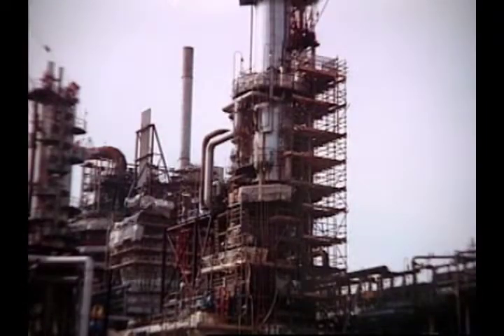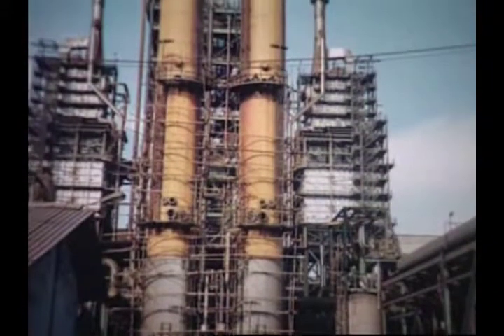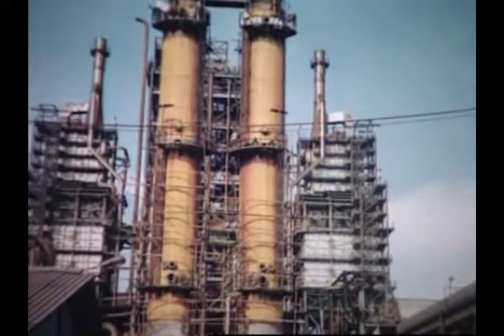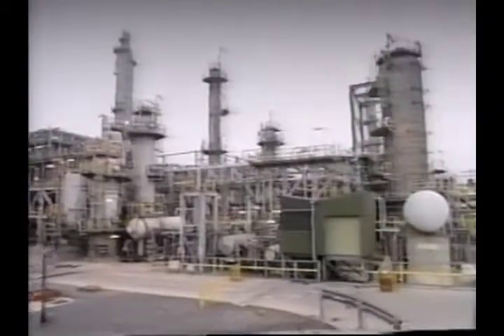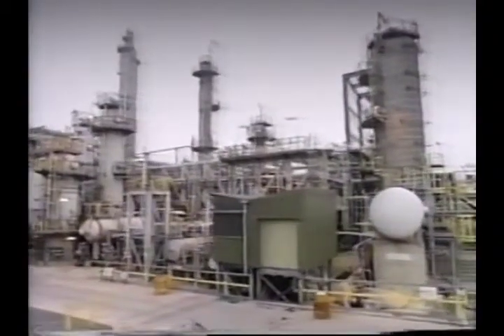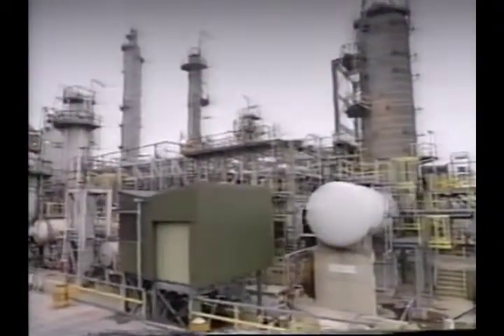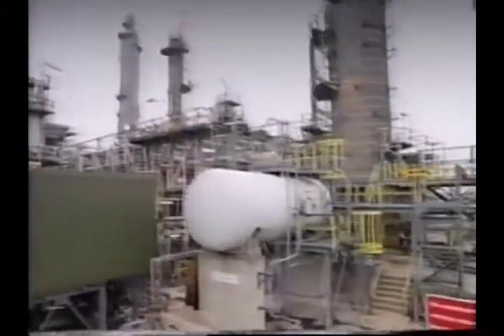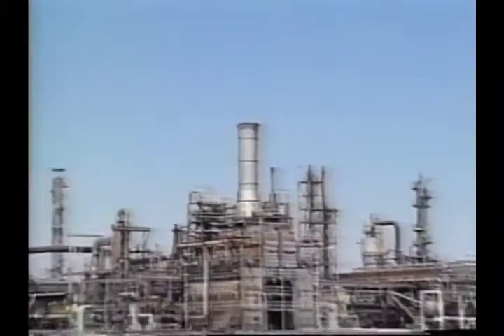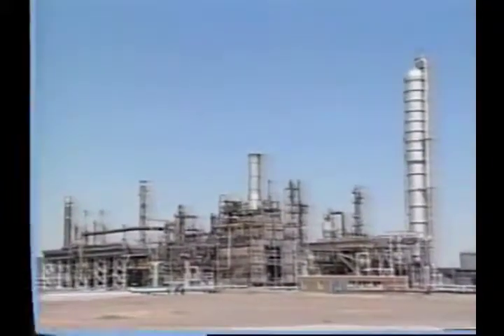The absorber towers in many plants are constantly under attack from the amine-based stripping process to remove CO2. The traditional strip lining or hot metal sprayed coatings are subject to attack from the carbonic acid formed during this process, resulting in failure due to stress, crevice, and galvanic corrosion. The use of traditional cold-applied coatings such as glass flake have either been discounted due to the elevated operating temperatures or, as experienced, has been destroyed during the steaming out process used to decontaminate the equipment during a plant shutdown.